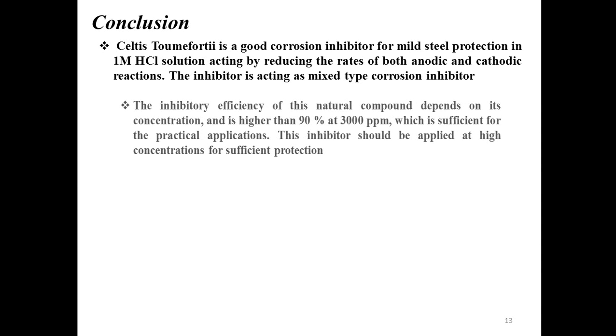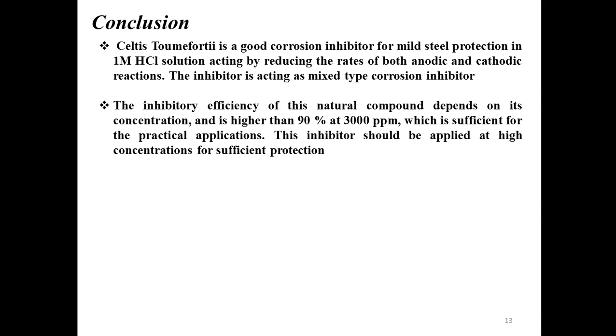Celtis tournefortii is a good corrosion inhibitor for mild steel protection in 1 molar HCl solution, acting by reducing the rates of both anodic and cathodic reactions. The inhibitor acts as a mixed-type corrosion inhibitor. The inhibition efficiency of this natural compound depends on its concentration and is higher than 90% at 3000 ppm, which is sufficient for practical applications. This inhibitor should be applied at high concentrations for sufficient protection.